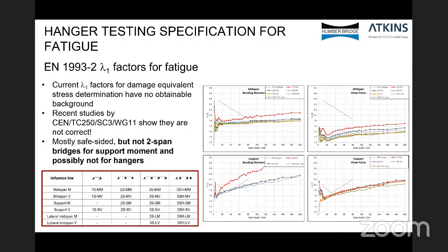So one of the things that happened during this testing is we'd specified the testing to be carried out in 2019. Now, during the actual testing of the first hanger, there was some research being carried out by the group that looks after the Eurocodes, working group number 11. And this found that the lambda factors, which are the factors used to calculate the damage equivalent stress, had no obtainable background. And because of that, there were concerns raised over the use of FLM3 during the assessment.